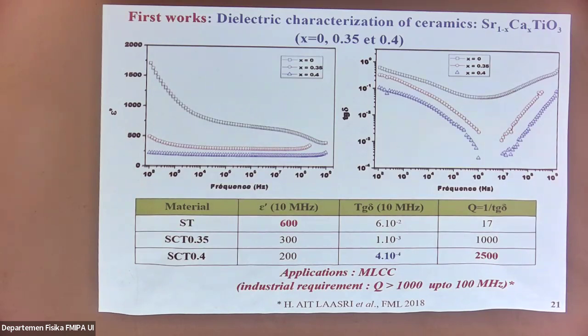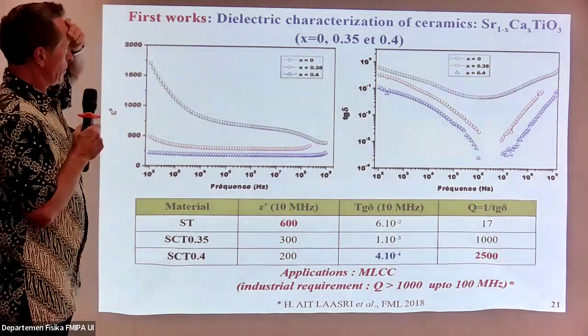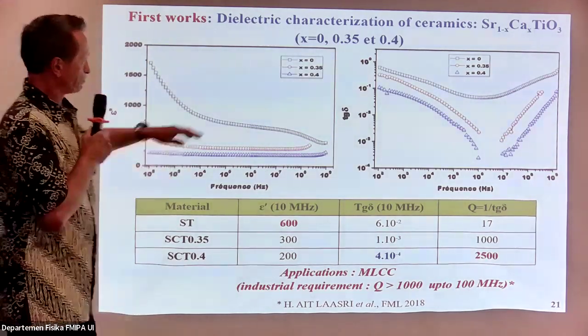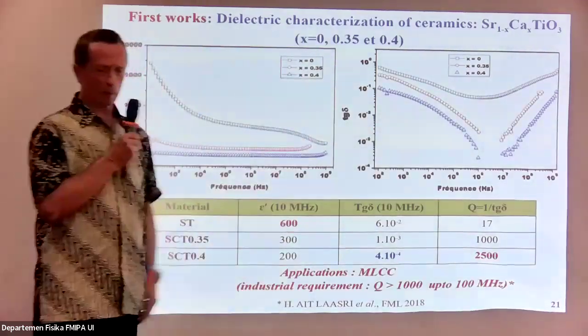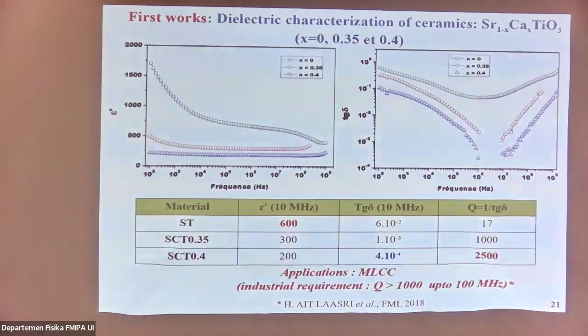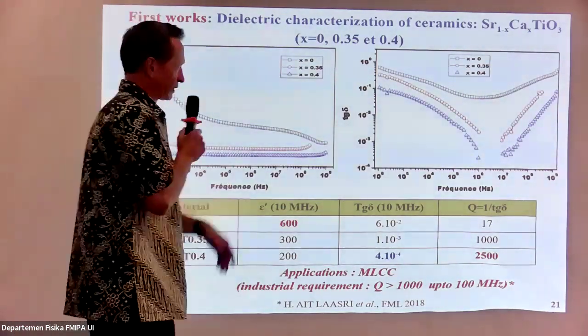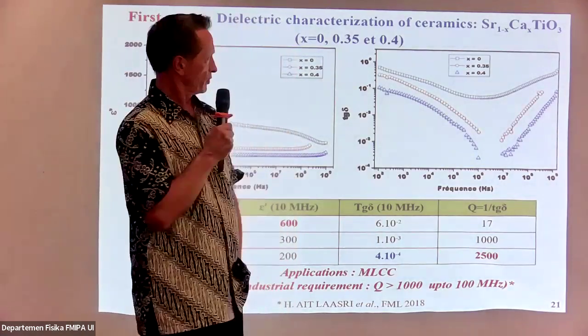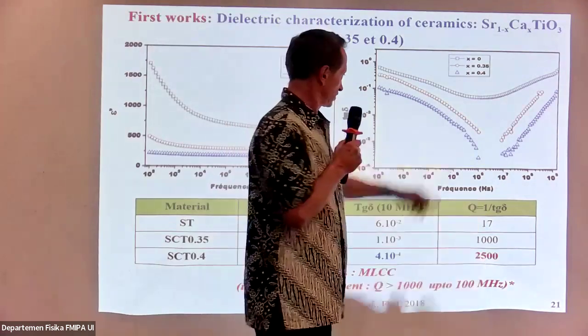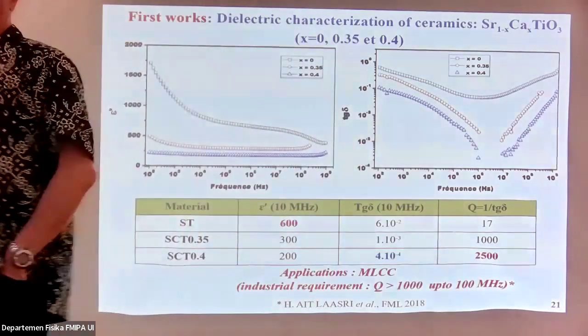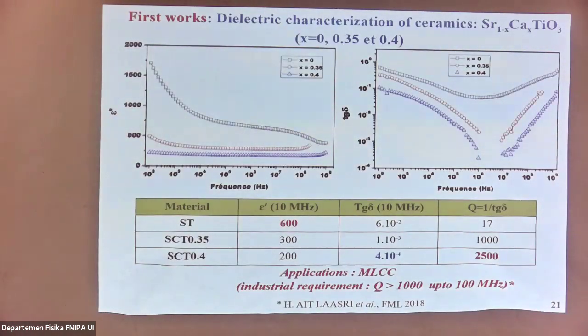It was in 2018 with one of my master students. At this time, I saw that it was very interesting to work around this doping rate with a maximum of 40% of calcium. Even if we decrease the dielectric constant, we saw that it was really possible to decrease the losses. Even if these responses were not ideal, because at this time we didn't optimize the ceramic, it was a very interesting preliminary result.